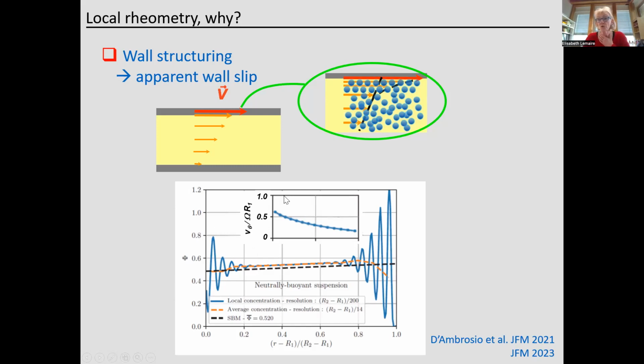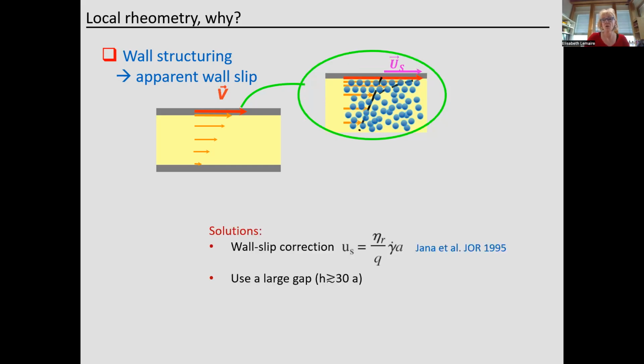So it's important to have in mind, if you make a rheometric experiment with non-Brownian suspension, that the particles are going to form layers, organize the layers near the wall. So you have some solutions if you cannot perform local rheometry. You can apply a wall slip correction as proposed by Jana, who gave an expression for the slip velocity.